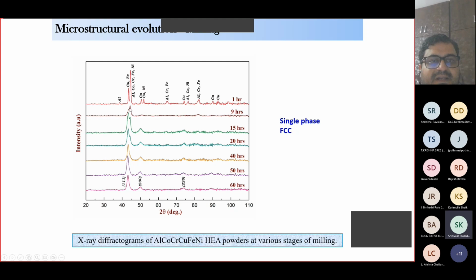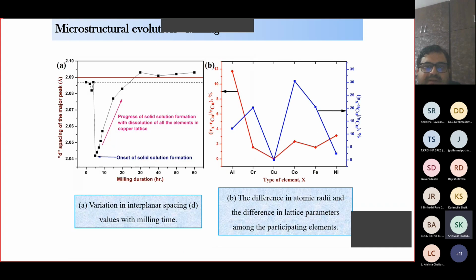See here, these are X-ray diffractograms. Initially you see the presence of all the participating elements. With the increase in milling time up to 60 hours, you see that you form a single phase FCC structure, which is really good. So all the elements went into one lattice and formed one, I would say, a host lattice, I would call that.